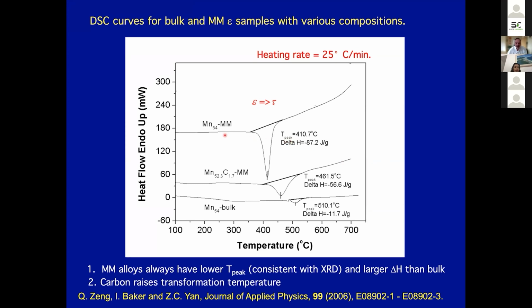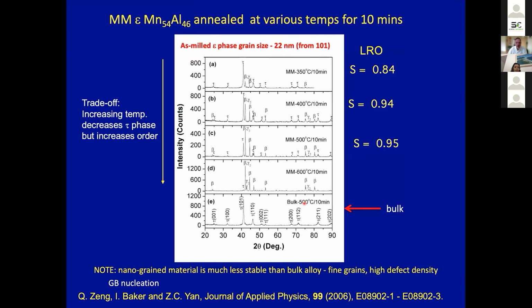Then if you run that material through a differential scanning calorimeter and compare it to bulk material, this is what you get. So this is the mechanically milled material. This is the bulk material. And you can see that the mechanically milled material has a lower transformation temperature and a larger energy associated with the transformation. The lower temperature is because the transformation occurs at grain boundaries, and there are many more grain boundaries in the material. Also shown here is the effect of carbon. Carbon also raises the transformation temperature a little bit compared to the bulk material.